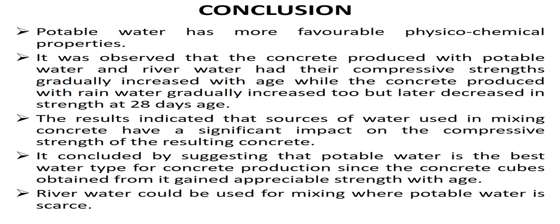Conclusion: potable water has more favorable physicochemical properties, as can be seen in Table 1. It was observed that the concrete produced with potable water and river water had their compressive strength gradually increased with age, while the concrete produced with rainwater gradually increased too, but later decreased in strength at 28-day age. The results indicated that sources of water used in mixing concrete have a significant impact on the compressive strength of the resulting concrete. It concluded by suggesting that potable water is the best water type for concrete production, since the concrete cubes obtained from it gain appreciable strength with age. River water could be used for mixing where potable water is scarce.